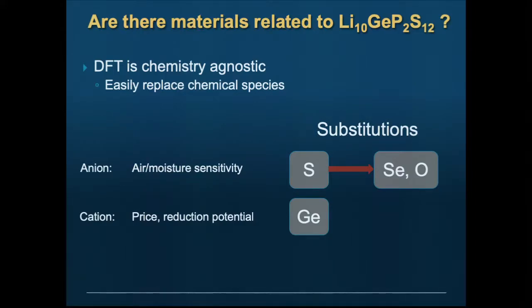To us, this was a proof of concept, so we right away started figuring out, can we replace sulfur? Sulfur is not great, right? If you expose sulfides to air, they make H2S, which is not a pleasant thing to work with. People are really worried about that in factories, because you can control it until something goes wrong. You get moisture infiltration in your process, and suddenly you have to evacuate the factory because you have toxic gases going around. This is actually not so much a problem in the battery. This is really a production problem.